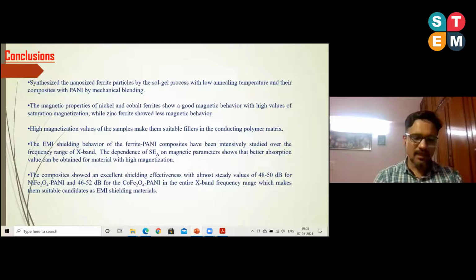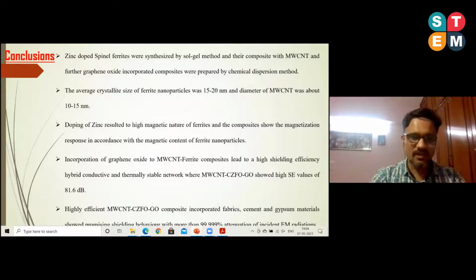So in the overall work, the aim was first to choose the appropriate filler material. That was the ferrite. The reasoning is, if you take any other magnetic material, it has corrosion problems, and at the same time degradation problems. So we selected the appropriate material, and cobalt ferrite and nickel ferrite are playing a very good role as filler material in the composite system. And we observed good EMI shielding properties for the nickel ferrite and PANI composite and cobalt ferrite and PANI composite. Then we modified the magnetic properties as we discussed above, and these modified magnetic properties and the suitable matrix system enhance the EMI shielding properties, and we got 81.6 decibel for the multi-wall carbon nanotube, cobalt zinc ferrite, and graphene oxide system.